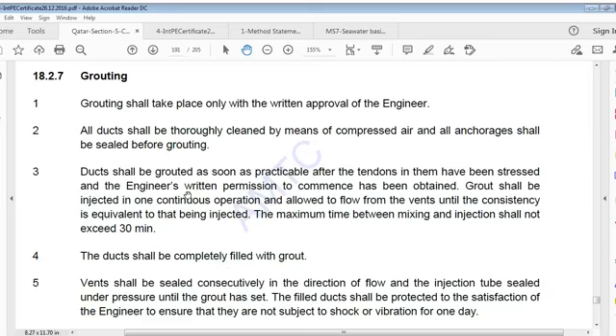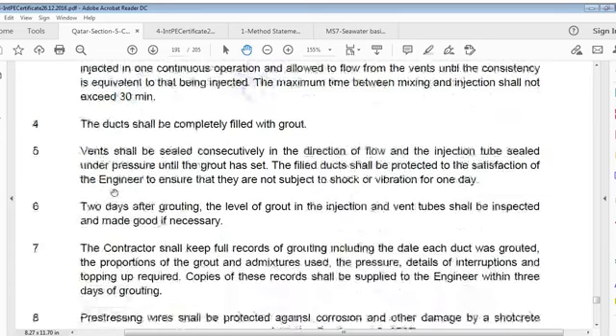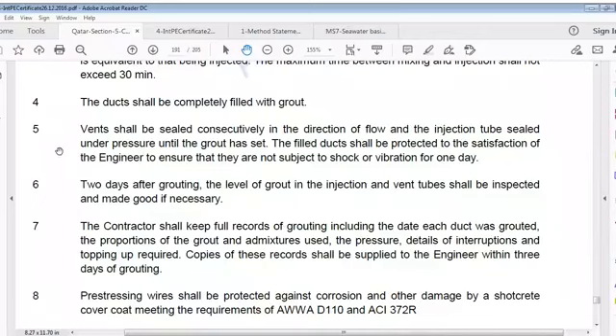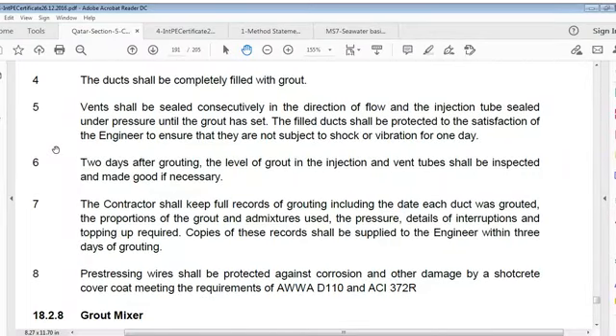Grout shall be injected in one continuous operation and allowed to flow from vents until consistency is equivalent to that being injected. Maximum time between mixing and injection shall not exceed 30 minutes. Duct shall be completely filled with grout. Vents shall be sealed consecutively in direction of flow and injection tube sealed under pressure until grout has set.